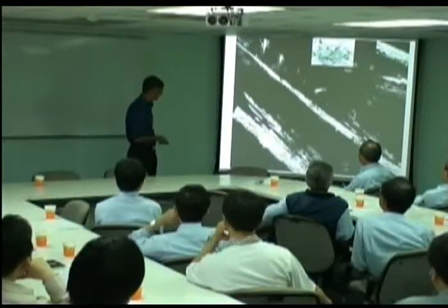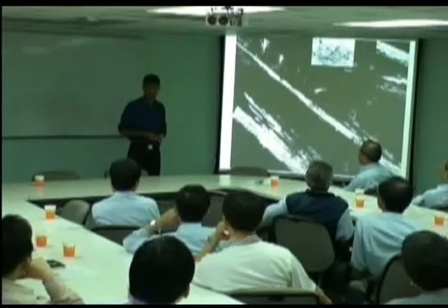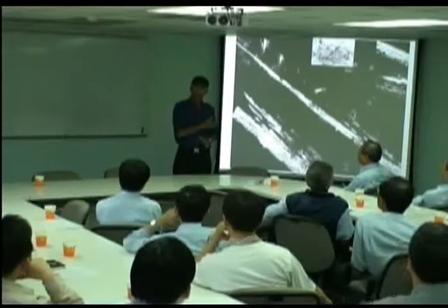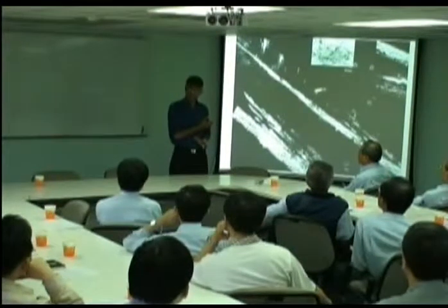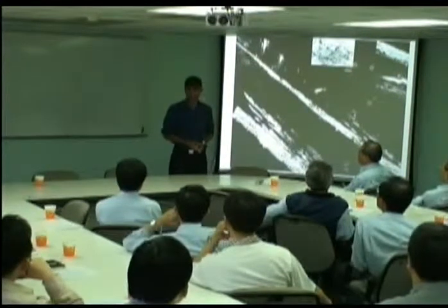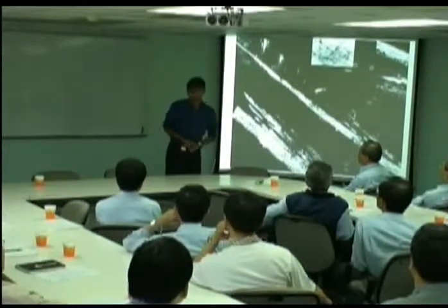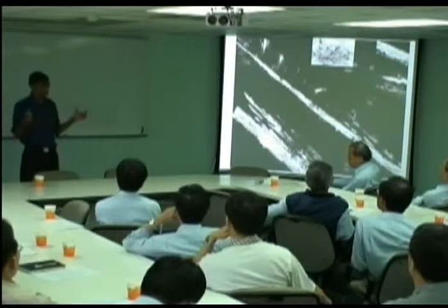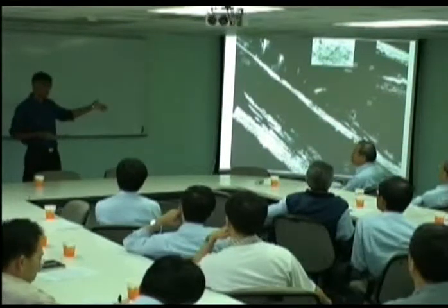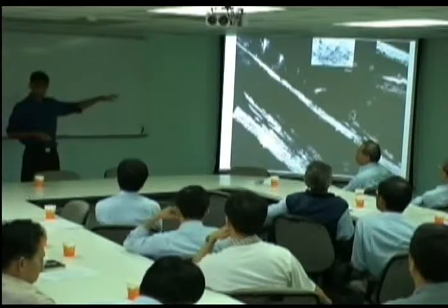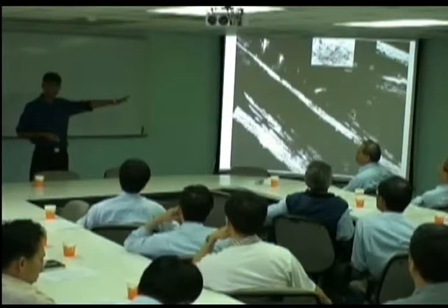And that's why the thickness remains around a quarter of a micrometer. Now, there is no thermomechanical process which can produce a grain size of a quarter of a micrometer. Here, you have a grain size of a quarter of a micrometer naturally by phase transformation. So the structure that we see inside this optical micrograph of bainite is actually thousands of very, very small platelets growing, stopping, and so on.